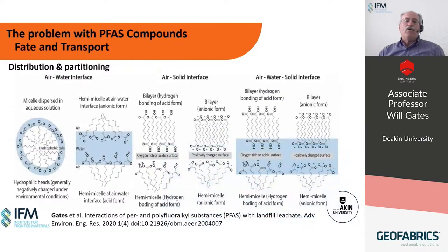For compounds like PFOA and PFAS, whose critical micelle concentrations and water solubilities are on a par, a key parameter for their partitioning and migration in the environment is their ability to concentrate at the interfaces. These interfacial micelle and hemimicelle films concentrate the PFAS at the interface, which then drives concentration-dependent equilibrium processes such as diffusion, adsorption, desorption, and partitioning to all the various phases.